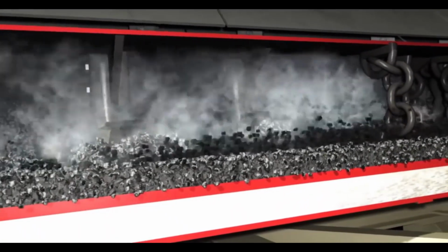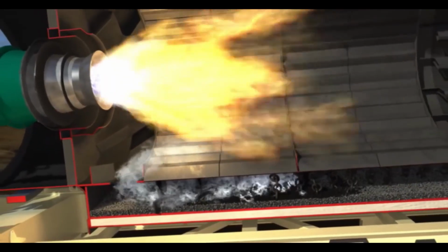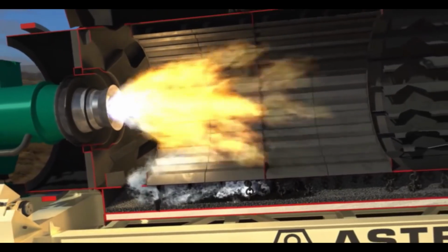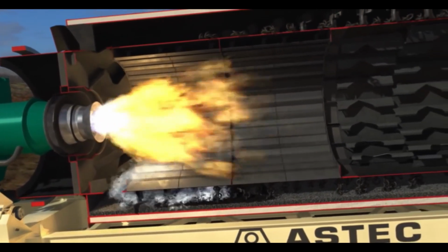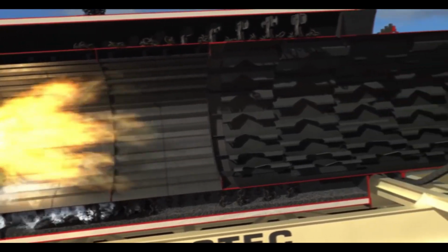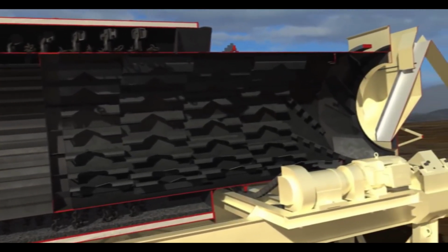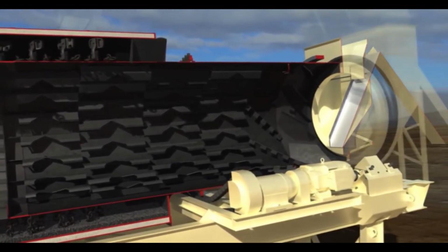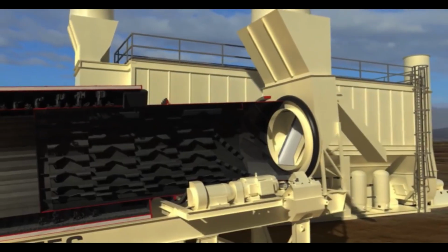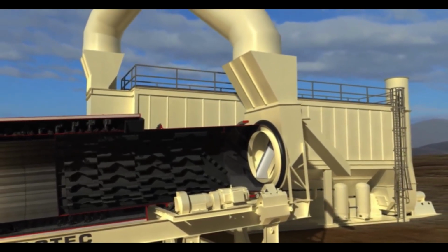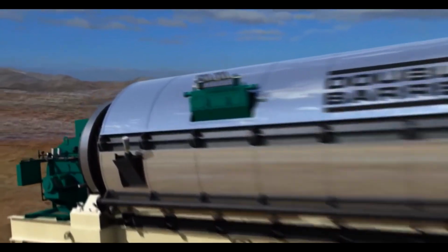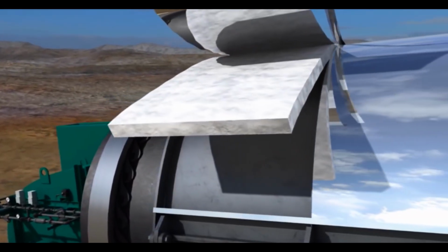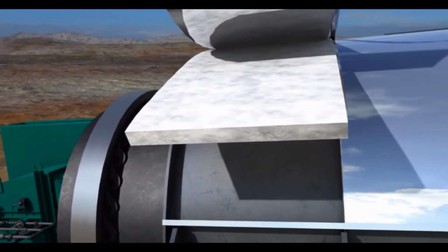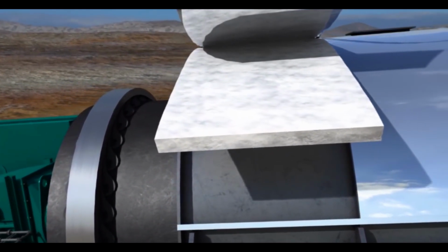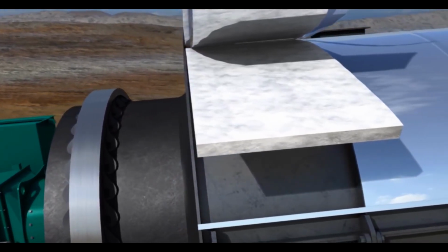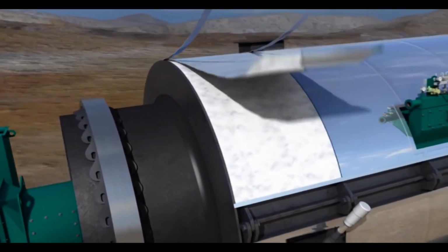The steam and blue smoke from the mixing chamber are pulled into the inner drum past the burner flame, where the hydrocarbons, or blue smoke, is incinerated. This results in a clear, odor-free stack. The only visible emissions are a steam plume on a cool day, even at 50% RAP. An insulated outer shell promotes efficient use of otherwise fugitive heat from the drying section. The use of the conserved recovered heat from the drying section of the drum translates into fuel savings.